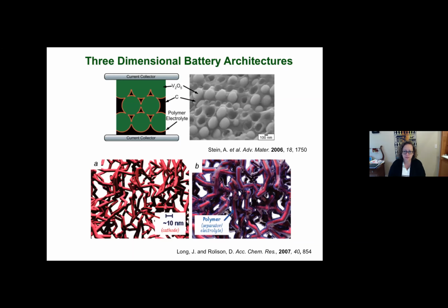On the top is an example from Andreas Stein at the University of Minnesota, where he uses silica spheres to create an opal structure, deposits carbon framework all around the silica spheres, and then chemically dissolves away the spheres. You fill the inside with a polymer electrolyte, a very thin layer, that's this orange layer right here, which is really thin. And then you fill in all the remaining void space, in this case with vanadium oxide as the cathode material.